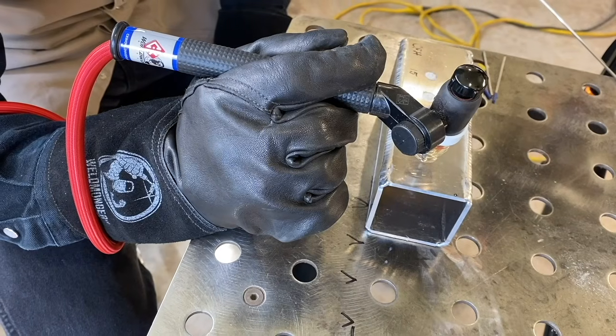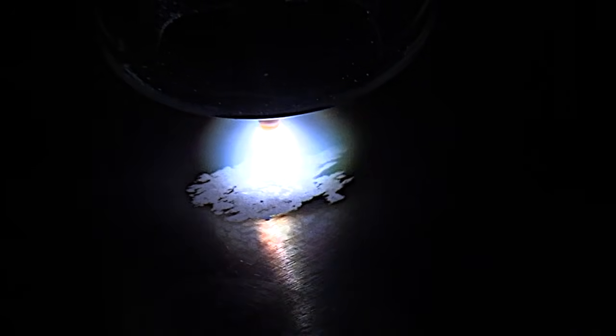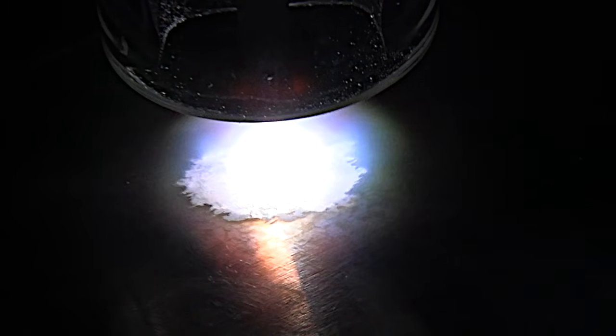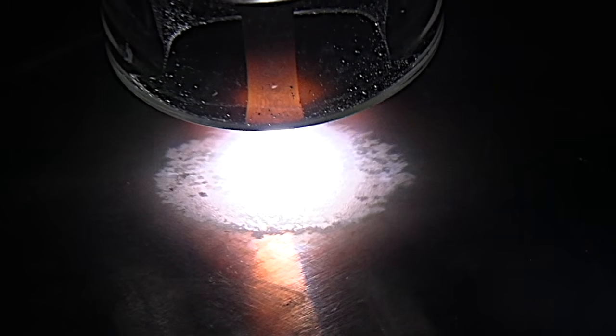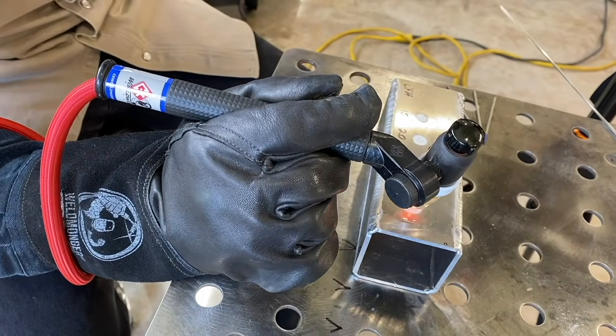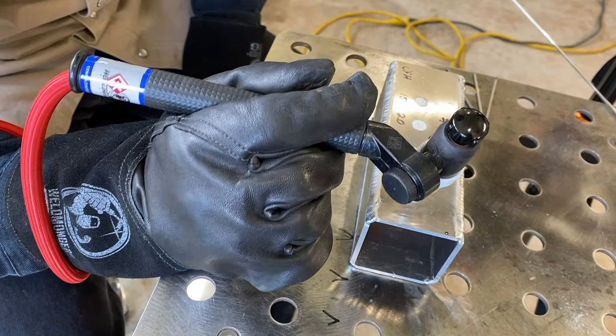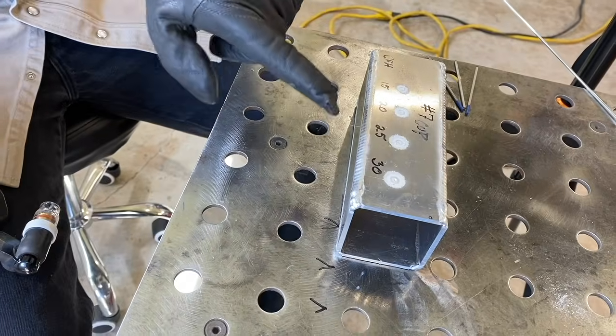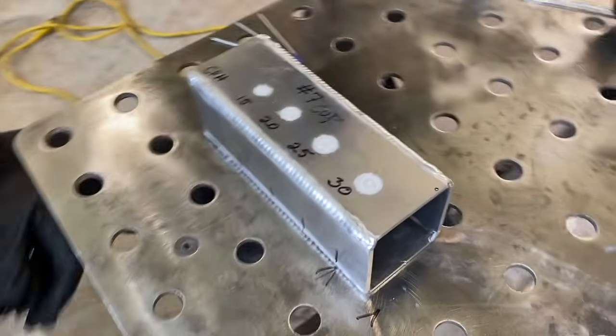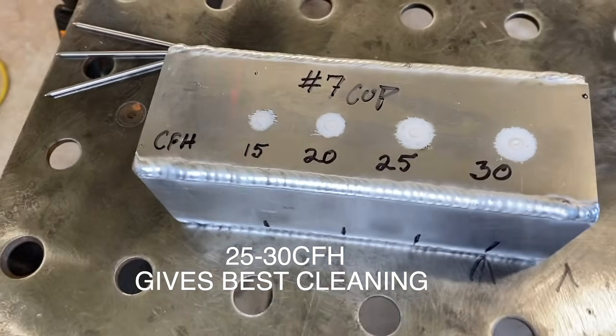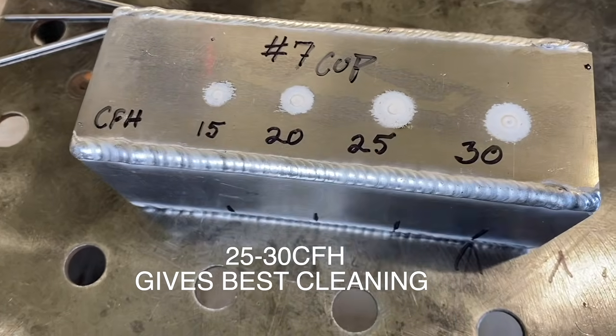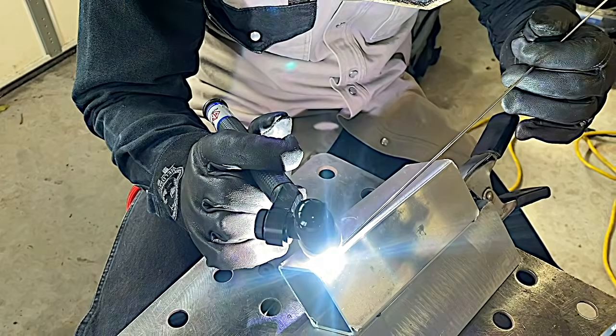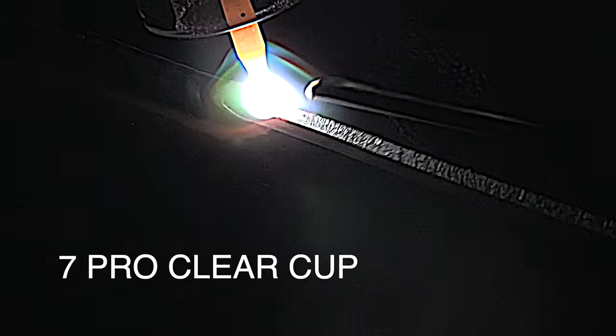Let's talk a little minute about gas flow rate and cleaning action. We were doing this outside corner joint here using a number 7 clear cup and getting a little milky puddle. So we decided to kind of test the argon flow and see what gave us the optimum cleaning path. Same cup, same AC balance setting. It looks like somewhere between 25 and 30 is the optimum setting there. So once we set it at about 28 CFH, the puddle cleaned up a lot.